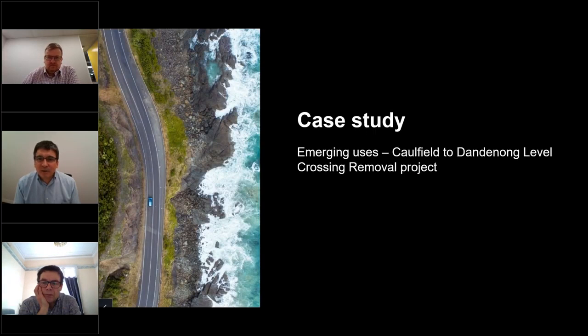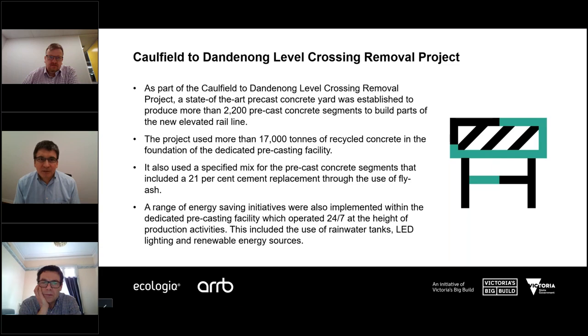So another one is the Caulfield to Dandenong level crossing removal project. Next slide, thanks. So often on these jobs, there's the need for temporary works. In this case, there was a precast concrete yard needed to be established, and this to produce more than 2,200 precast concrete segments for the Skyway, for the rail line, elevated rail line. So for these temporary works, more than 17,000 tonnes of recycled concrete were used in the foundation, and also a specified mix for the precast concrete segments included 21% cement replacement through the use of fly ash, another recycled waste product.